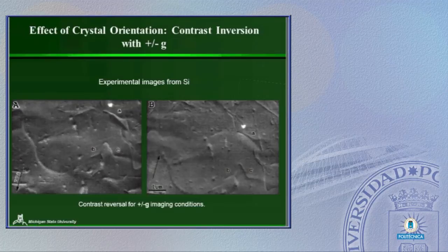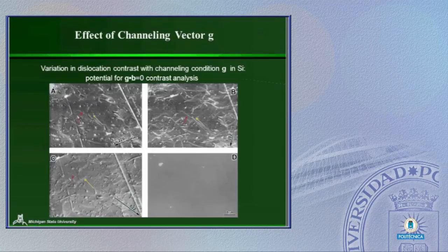A couple of other things. If you're familiar with TEM, you can imagine setting up diffracting conditions with a minus G condition or a plus G condition. The same sort of situation occurs. We get a reversal in contrast. We can see, for example, we go from here dark to bright. Here we go bright to dark, which really makes sense because we're saying one side of the dislocation is giving us a dominant diffraction rather than the other side of the dislocation.